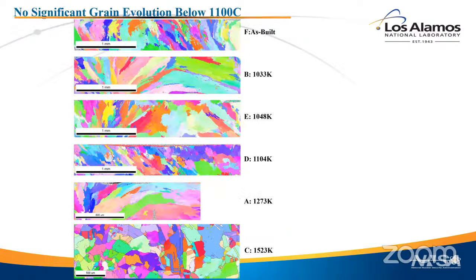Another one was the grain morphology, right? So in the as-AM material, sample F up on top, you see that tortuous microstructure. And as you heat treat it higher and higher, by A, the size scale maybe has changed. That might more be A, B, C, D, E, the position that it was grown.